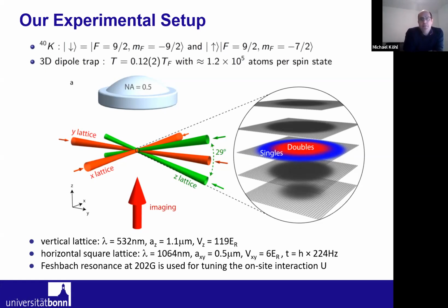The detection is done by absorption imaging. So the sample is then illuminated with a laser beam from the bottom, and through a high numerical aperture microscope, we look at the density distribution of the atoms in the lattice. So in this experiment, we do not have single site resolution. It's a very good microscope, but not enough to really observe the single lattice sites. But I will show you later in this talk that we actually don't need single site resolution in order to see the antiferromagnetic correlations.